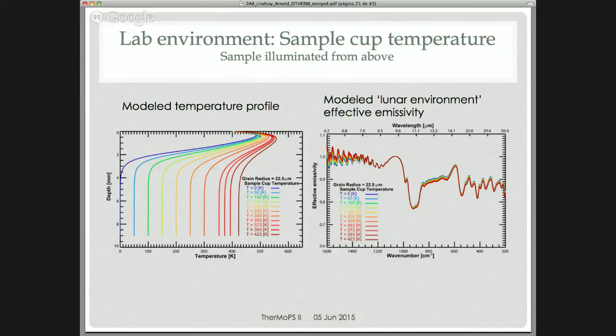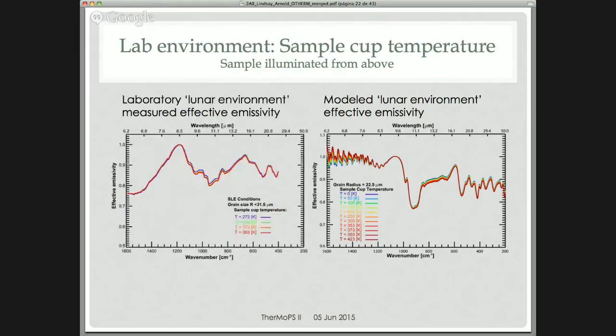Now comparing the modeled emissivity spectrum here to what we actually measure, we can see that our sample cup temperatures are going from 272 to 393, and that corresponds to the red in the model plot. And we can see that in both cases, in the lab measured and the model, the sample cup temperature doesn't have a huge effect on the emissivity, especially at the Christiansen feature, maybe a little bit in the Reststrahlen bands.